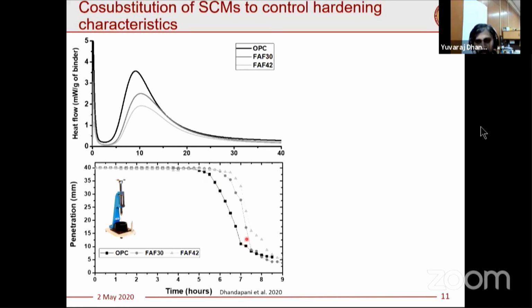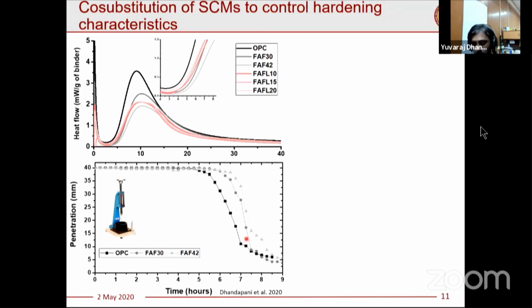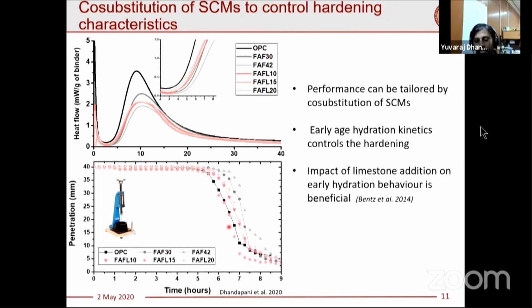So when you start adding a minor dosage of limestone, Pranoy talked about limestone being a filler. Despite being an inert material, it can accelerate the reaction of the clinker. So you can see the heat flow start becoming much closer to your clinker reaction. So when this happens, the setting time can be brought closer to your PC systems. So the performance can be tailored by proper co-substitution of SCMs. The early age hydration kinetics can be controlled, and the hardening characteristics can be fine-tuned. And in general, the impact of limestone addition on the early age behavior is quite beneficial, which has been widely talked about in literature as well.